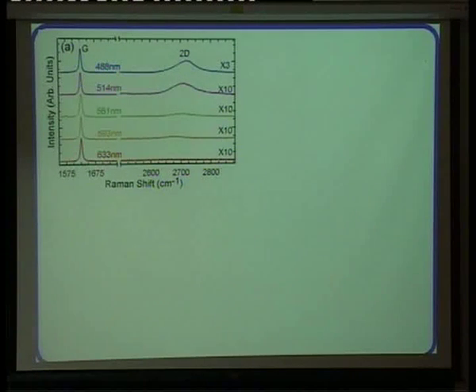So before we looked at what happens for a given sample, for a given excitation energy, when we change the doping level with this Debye layer and so on. But now what happens when we have a given doping level, because we have an intercalant, so we can only dope so much, but we do change the excitation energy. And so what we see is the intensity of the 2D peak can be very large at one excitation energy, and completely zero at another excitation energy, but it's exactly the same sample. I'm not changing the sample, I'm changing the excitation energy.